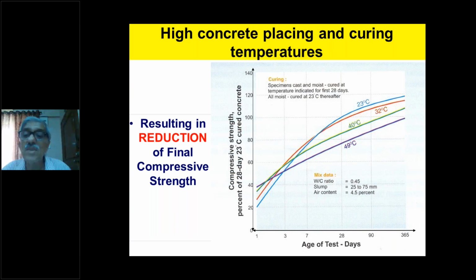Okay, I continue further. And if you see here, these four curves are there. The temperature 23 degrees centigrade is the lowest. So it starts with a lower strength and goes higher and higher, overtakes the other strengths. 49 degrees is the hottest concrete, which is not very recommended to do. Then there is a concrete done at 40 degrees and concrete done at 32 degrees. So all these four curves are there.